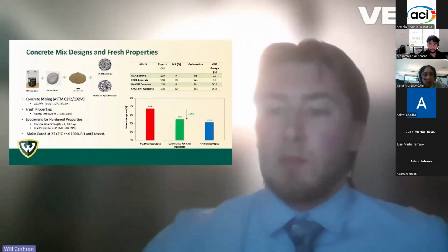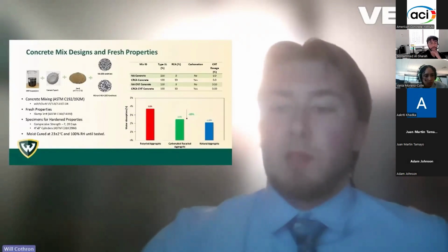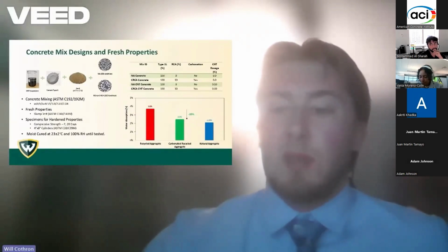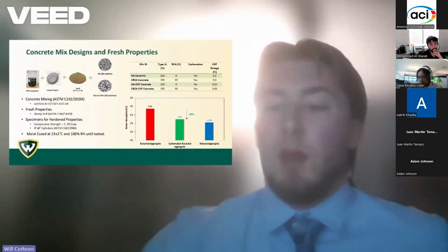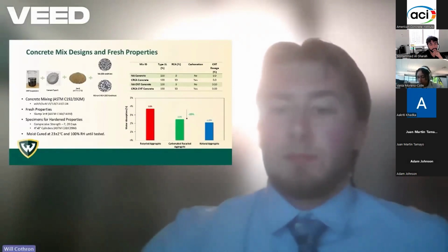The concrete mixes were prepared according to ASTM C192 standards, and the fresh concrete's workability was measured using the slump test, ASTM C143. For evaluating strength, we cast concrete cylinders 4 inches by 8 inches, cured them at controlled conditions, and tested their compressive strength after 7 and 28 days, following ASTM C39.